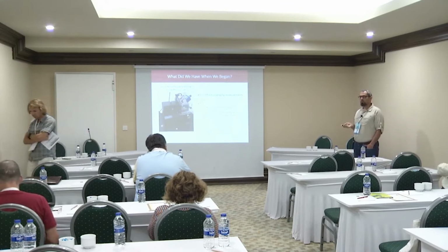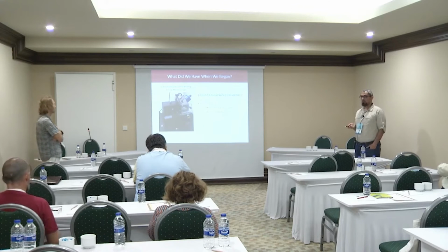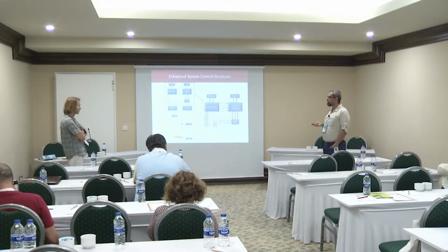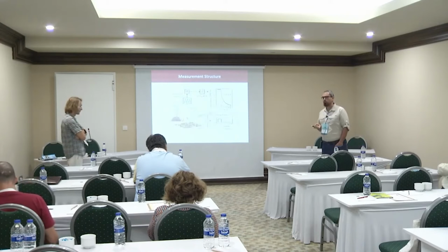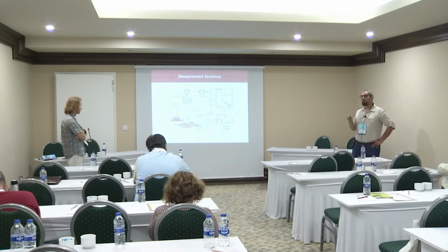Okay, so the experiments that you performed, yes, the temperature-dependent experiments, were they performed under vacuum? Strontium titanate experiments, the first experiments, they were conducted under vacuum conditions, but for titanium dioxide measurements, which we had to induce oxygen vacancies, they don't work under vacuum conditions because we need water in order to reduce surface. So they were conducted under ambient conditions, but in a controlled atmosphere.